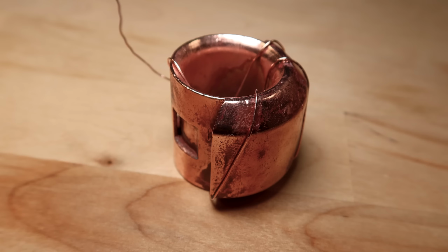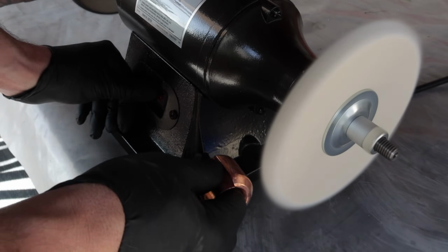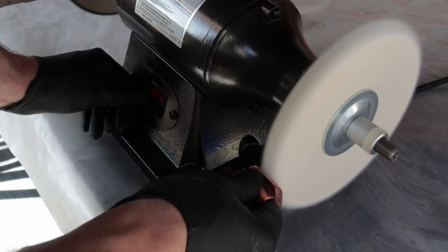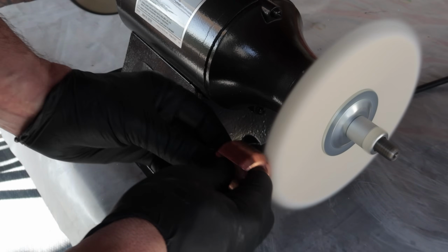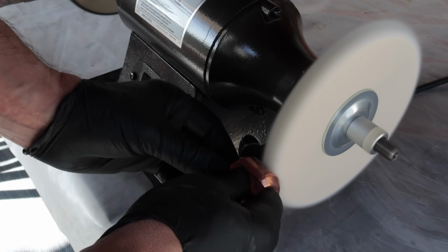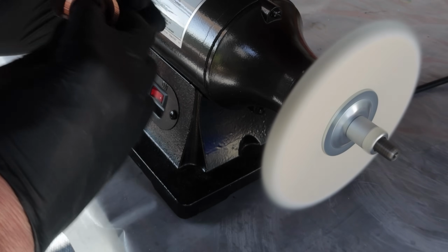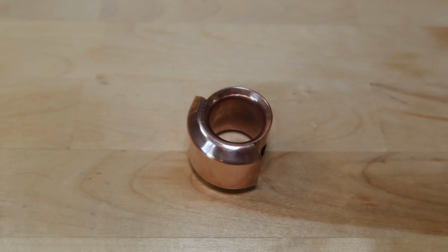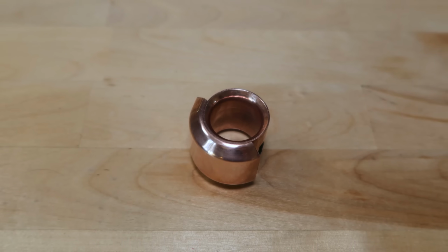I pulled the ring out of the electroplating bath and the results came out a lot better than even the lattice parts I did earlier. Still a little rough in some areas, but this will polish off to a super bright surface. This part's also big enough to use the buffing wheel instead of the Dremel. This is great because it's a lot faster and it's a lot easier to get a uniform polish across the piece. And with that, all my electroplating parts are done.